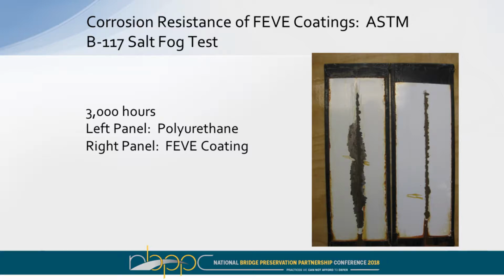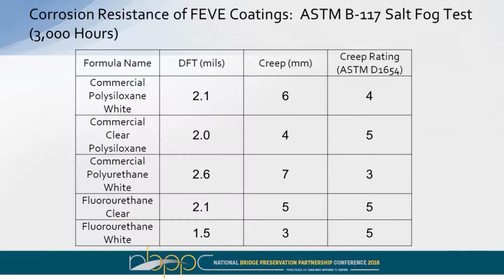Again, this is the salt fog test after 3,000 hours, and this is just in table form basically. And a 5 is considered excellent results, and then 3 is average. It goes all the way down to 1. I think it may even go to 0. But you can see all of these different systems have adequate corrosion protection. The fluorourethane does appear to outperform the other coating types in this test.